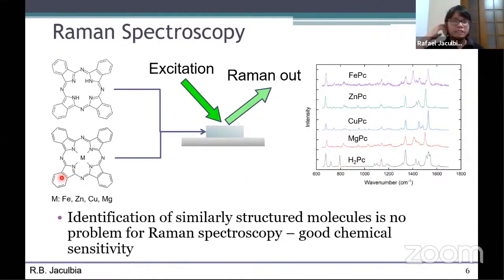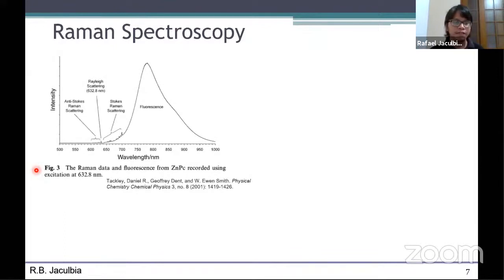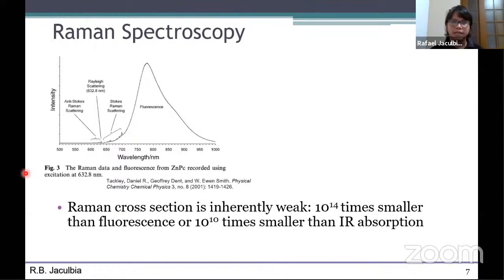So as I said, the identification of similarly structured molecules is no problem for Raman spectroscopy. We always say that Raman spectroscopy has a good chemical sensitivity, so it can identify different structures. However, Raman spectroscopy, as I described previously, is very weak. Here is a Raman and fluorescence spectrum from zinc phthalocyanine. You can see a very large fluorescence background and just very weak Raman signals, both in the anti-Stokes region and the Stokes region. So Raman is very weak. In fact, it's about 10 to the 14 times weaker than fluorescence and about 10 to the 10 times weaker than IR absorption.